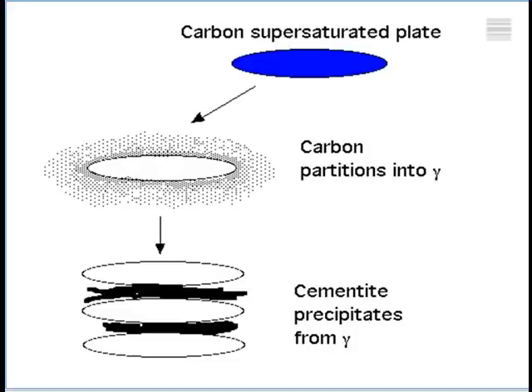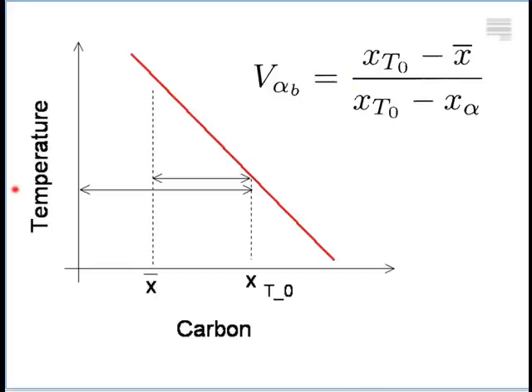Okay. The implication of this from thermodynamics is that bainite will stop forming when the carbon concentration of the austenite reaches a particular value called the T0 value, okay? So I don't want you to worry about the details about the T0 value. I'll illustrate what that means.